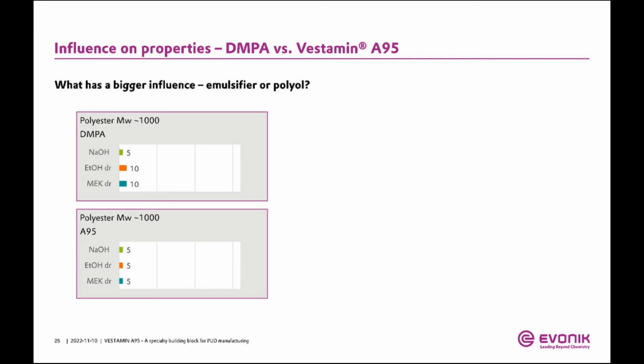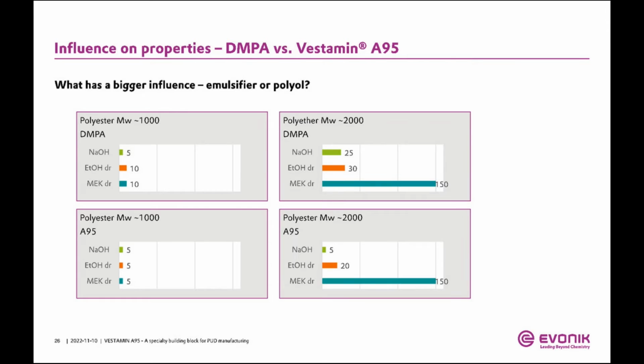Yeah, the resistance against certain chemicals: sodium hydroxide solution, double rubs with ethanol, and double rubs with MEK. So they survive not very many of these double rubs if you choose this very soft PUD without any hard segments. If you now just exchange the resin again and don't do anything else, you'll see that the impact of your resin is way, way, way higher, right? So here you can improve your resistance drastically in both cases. And the effect of your polyester and your building blocks here is way, way higher than it would be just by exchanging the emulsifier.